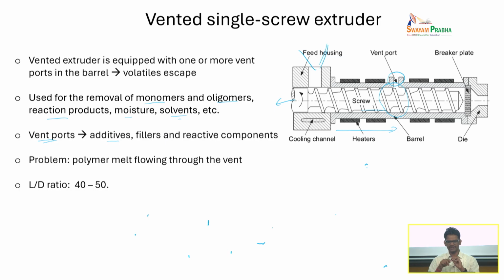Now, one problem with this vented single screw extruder is that sometimes when the screw is operating, it's increasing the pressure. Sometimes the molten polymer can also come out of this. Okay, if the orifice is big enough, the polymer can also escape through that. So that is something that you have to be cautious about, and that's why you see here the diameter of the screw is now decreased, so that the pressure can be reduced locally, so that only the volatile goes out and the polymer does not go out. Okay, so that's something we have to keep in mind.